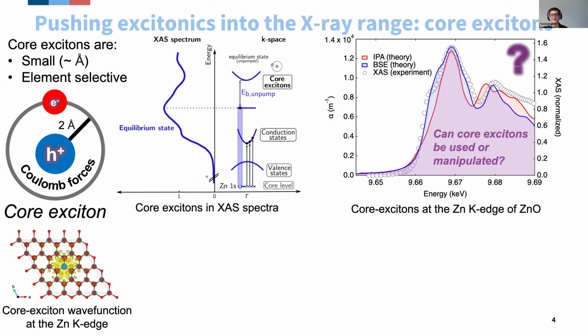And the reason why they are element selective is simply because these excitons are formed between a hole in a core level and a valence electron, and they're coulombically bound together. The binding energy of these two particles is actually way more than what you get in the optical regime. We are talking about binding energies of typically several hundreds of milli-electron volts in this case. They are extremely small. I, for instance, depicted here a calculated excitonic wave function in zinc oxide, and you can see a spatial representation of the electronic density in the exciton in yellow, and you can see that the dimensions are typically of the order of interatomic bond distances, so they are way smaller than what an optical exciton is in terms of dimension.